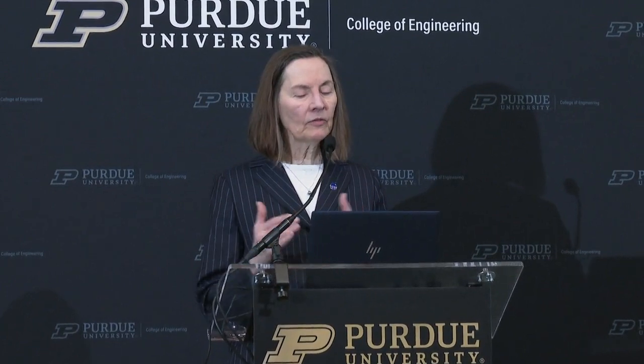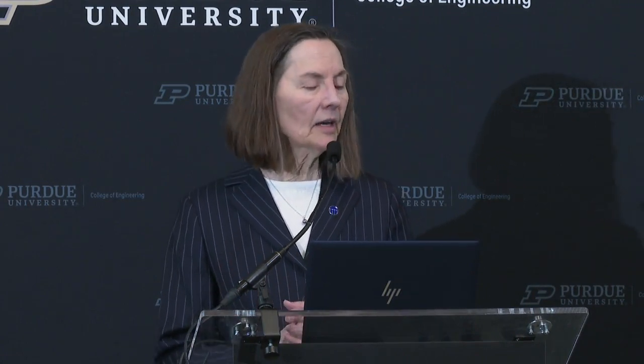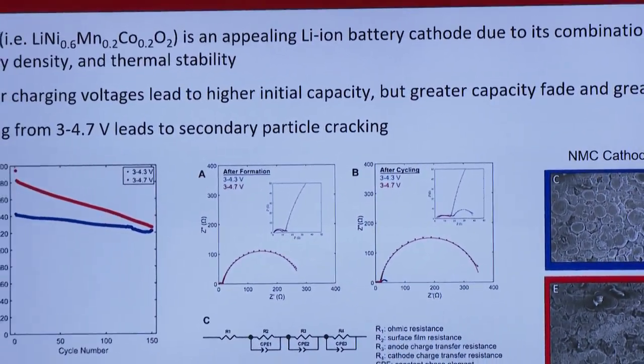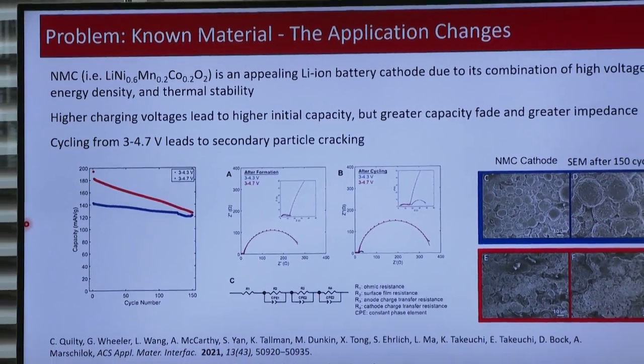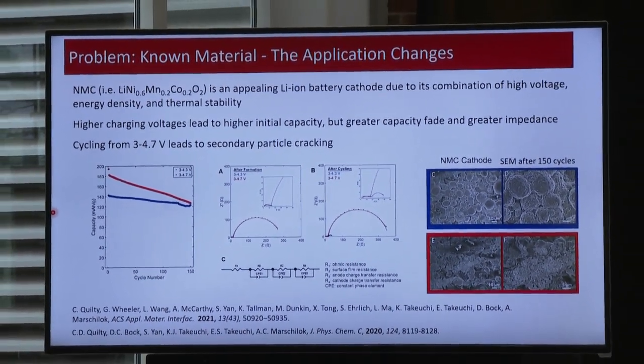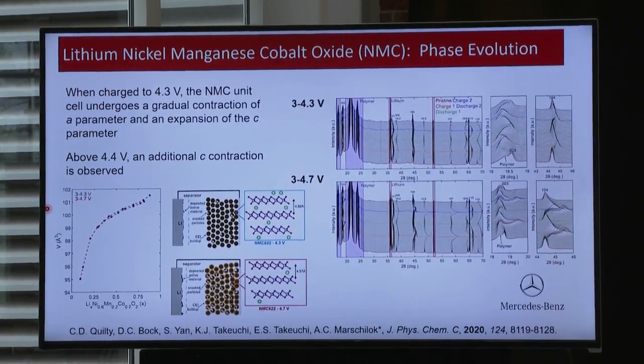So the amount of energy that you can get out of NMC depends on the lithium content. If you pull more lithium out by charging it to higher voltage, you can, in fact, get higher capacity, about 20% higher. So we cycled batteries charging to 4.7 versus 4.3 volts, and the 4.7 ones are degrading a lot. The capacity is fading, and we knew that we had increased impedance. We also observe particle cracking that's a little bit more exaggerated when the materials are at higher states of delithiation. So we wanted to understand that more.